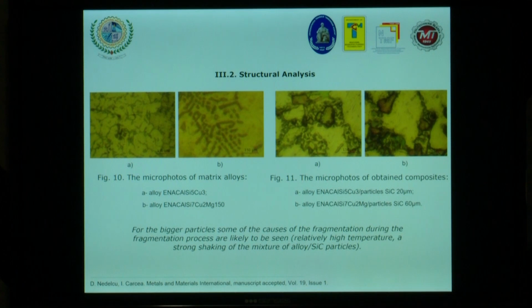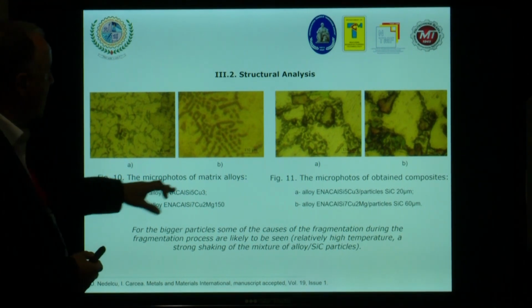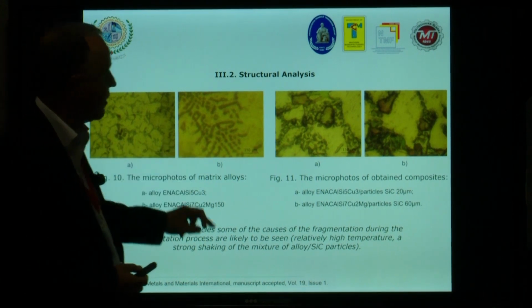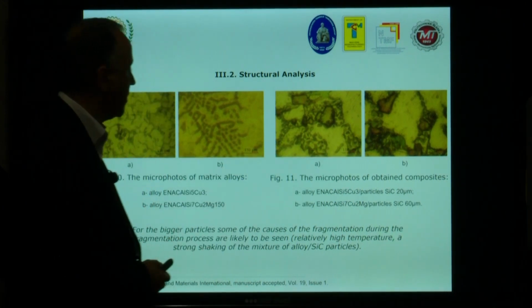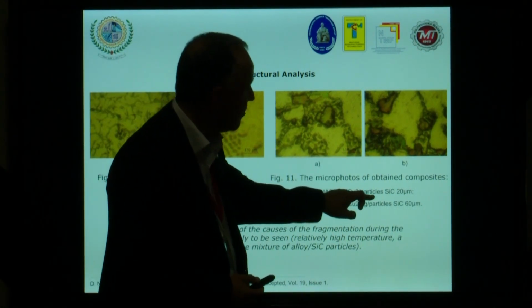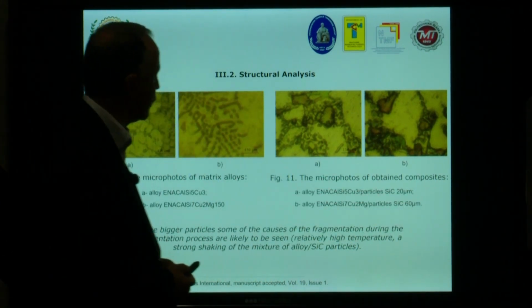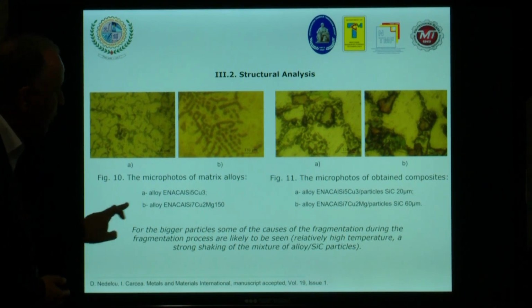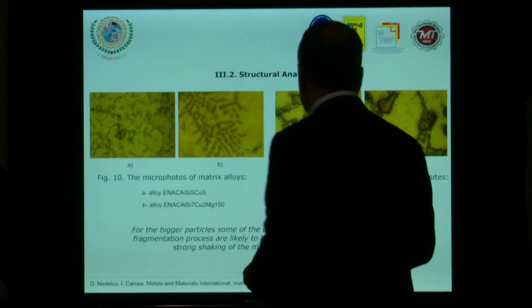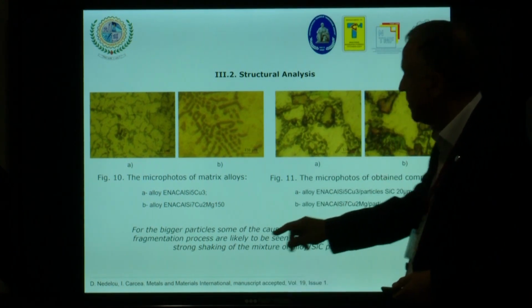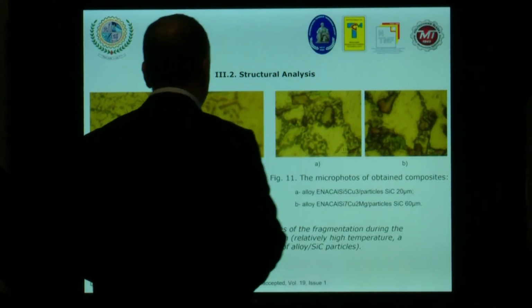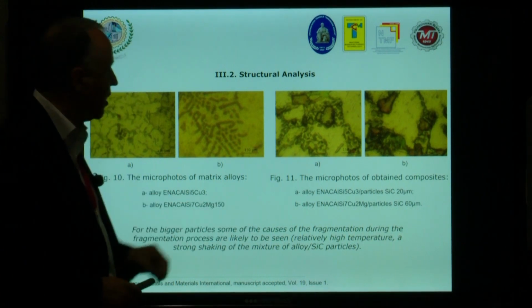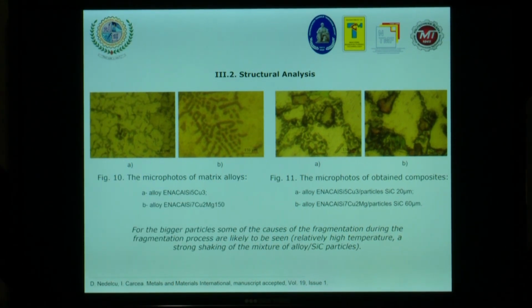Structural analysis. Here is the structural analysis of the matrix alloy, first alloy here, second one, and some microphotos obtained for the composite, also first alloy, second alloy. Of course, we reinforced with particles of 20 micrometers and 60 micrometers. The main conclusion for the bigger particles, I mean 60 micrometers, is that some of the causes of fragmentation during the process are likely to be seen. I mean the relatively high temperature and strong shaking of the mixture of alloy reinforced with silicon carbide particles.